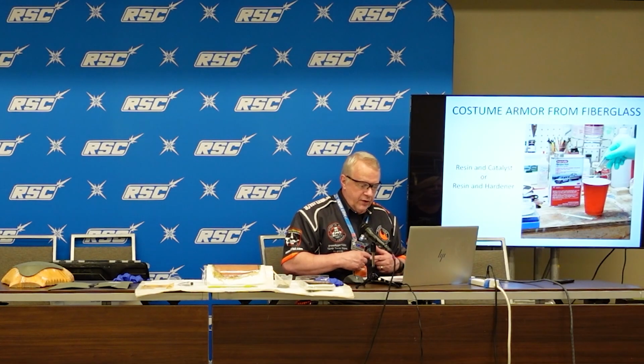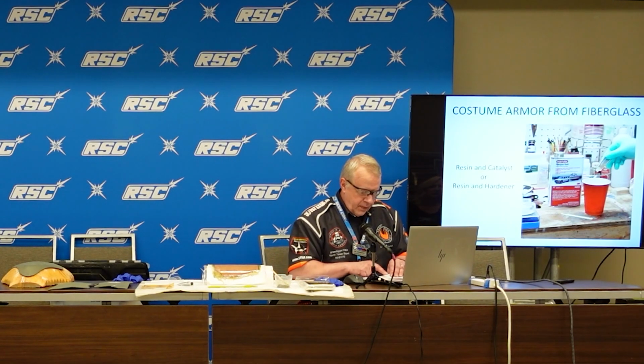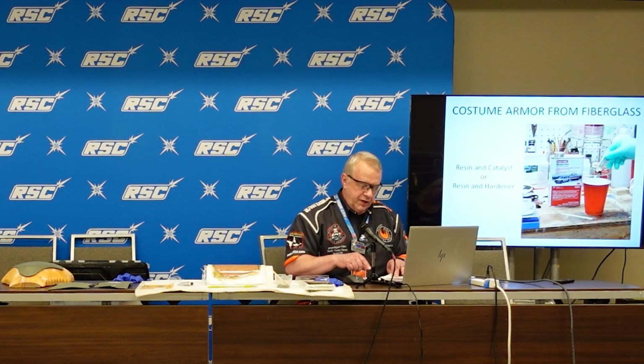The other thing I wanted to talk about is the temperatures, okay? So 12 drops of catalyst per 1 ounce of resin is great for 70 degrees, with about 10 minutes of work life. If it's 90 degrees out with 12 drops, you may only get about 9 minutes of work life. So you can reduce the number of drops of catalyst to increase your working life. But if it's 40 degrees, 12 drops of catalyst will give you maybe 15 to 20 minutes or longer of working life. But it won't fully cure for hours.